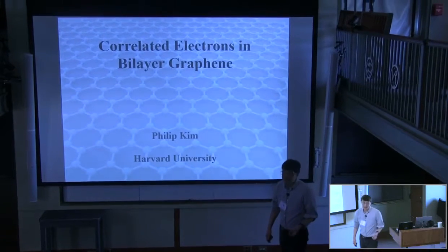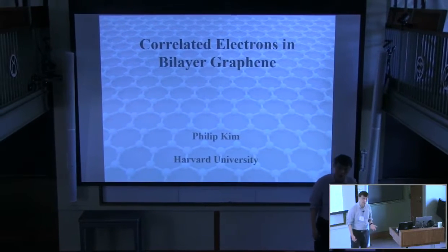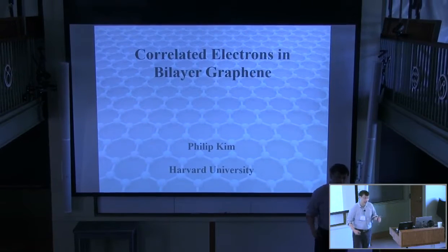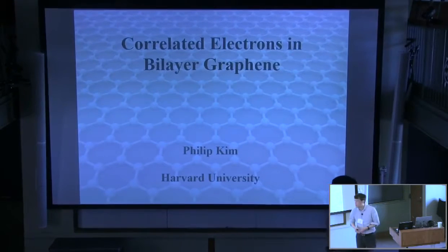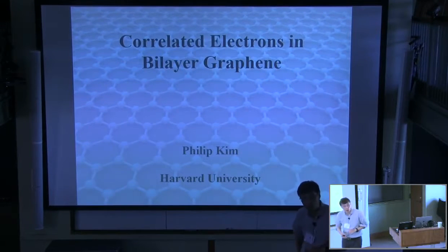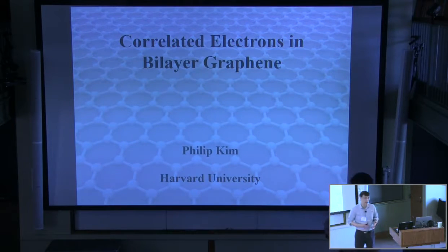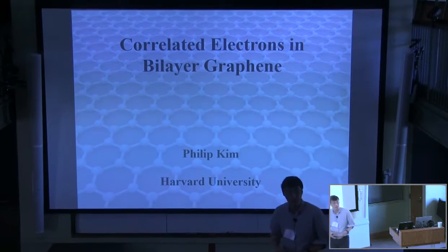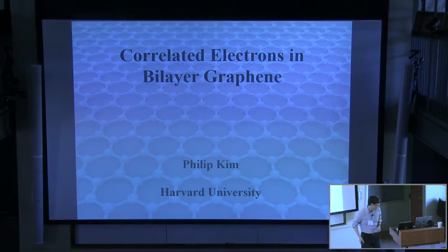structures. Graphene, well, the mobility is probably barely about a million in the best case, so this is 30 times worse. Maybe we can say this is slightly more correlated, and the correlation tends to be stronger because there is less dielectric screening. It can be suspended or it can be put into low dielectric screening environments. So you can promote correlations, but nevertheless, in the bottom line, we have not seen, or probably people have not seen yet, the new fractions, let's say. We are not aware of any from the gallium arsenide to that.